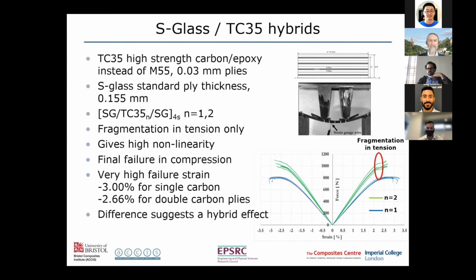One reason is because it's a bending specimen, and in a bending specimen, the strain gradient through the thickness can increase the failure strain. But also, we think there's a hybrid effect in that the carbon fibres are supported by the adjacent glass, and therefore this inhibits the shear instability microbuckling type of failure which you typically get with carbon fibre. And you'll see that the strain actually is higher when we have a single carbon fibre layer compared to a double layer, and that suggests a hybrid effect where the smaller the proportion of the carbon relative to the glass, the higher strain you can go before it exhibits a compressive failure.